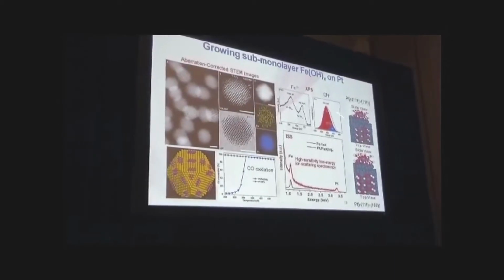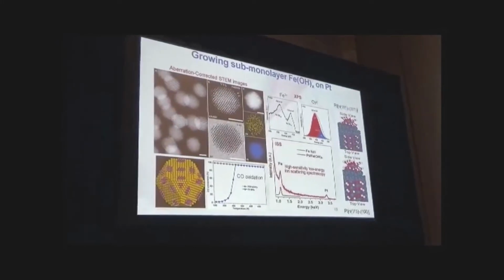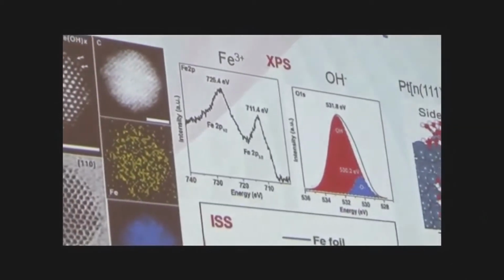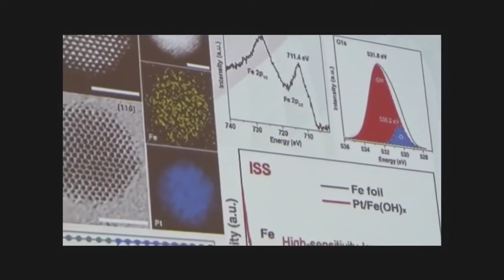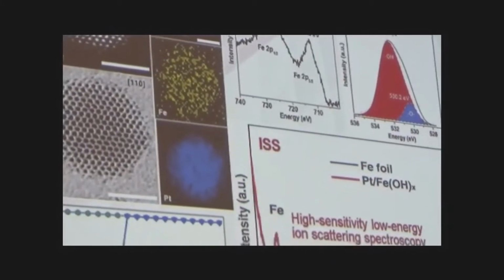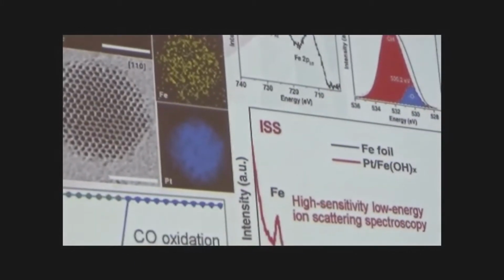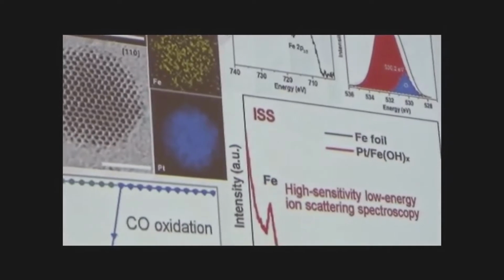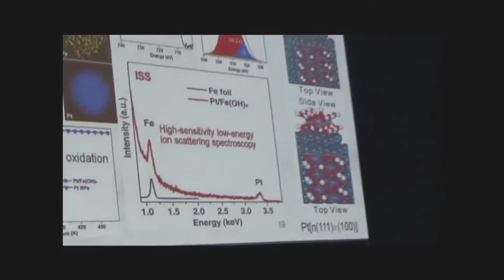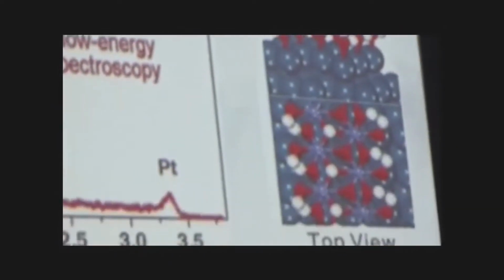From the XPS, we can see that iron is 3+, and the ratio of OH group to O is about 9:1. From the ISS, ion scattering spectroscopy, we can see that Pt is still exposed on the surface. So we build such a model. In this model, here is the iron hydroxide, and here is the Pt.